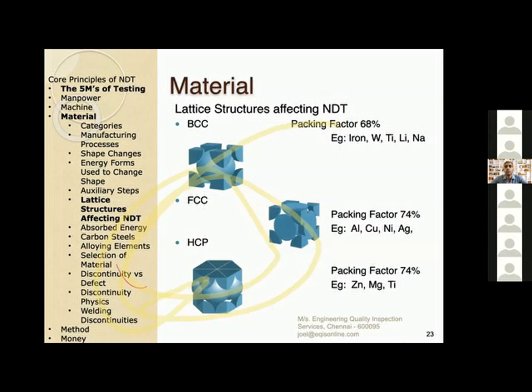I will be looking for defects that come from its alloys. Like for example, there'll be a small content of carbon, probably manganese, and all these processes are going to have oxygen trapped at some point or the other. So when there is an oxygen trap, then it's more prone to rust. So that's why our low alloy metals, the surface gets oxidized very quickly. So I'll have to look for an NDT method that will help me deal with a coating that prevents me from doing NDT properly. So then I have to remove the coating to perform an NDT and again have the coating back on it. So these are the parameters that affect the NDT directly.